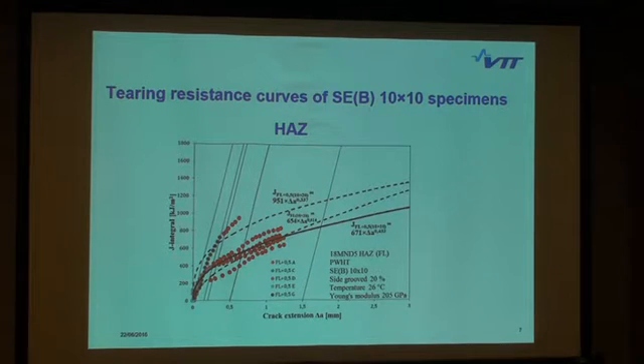And the last case, the last location, is the heat affected zone side. We have once again the black line, which follows the fitting that's been done to this bunch of data. And then we have, okay, so we are on the heat affected zone side, the 10 times 10 specimen following this line. And once again, there's a difference in the tearing resistance. But as seen in these pictures, this data seems to follow quite well the 10 times 20 specimens that have been manufactured on the fusion line.